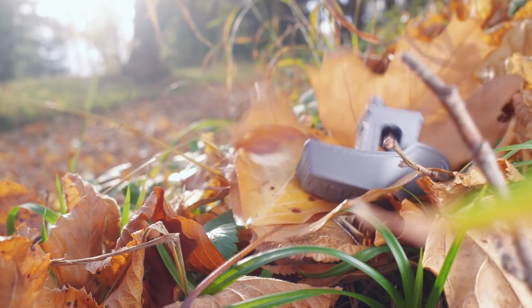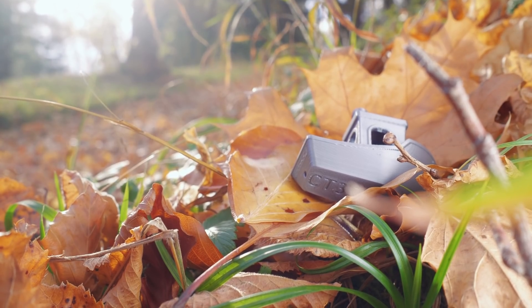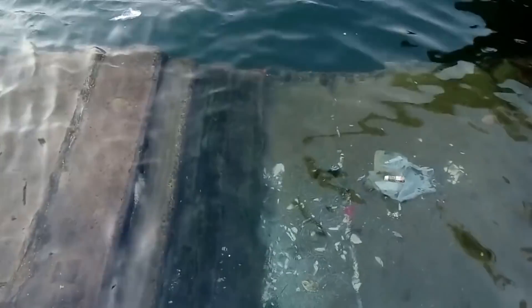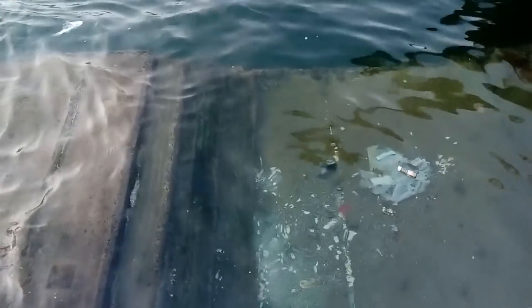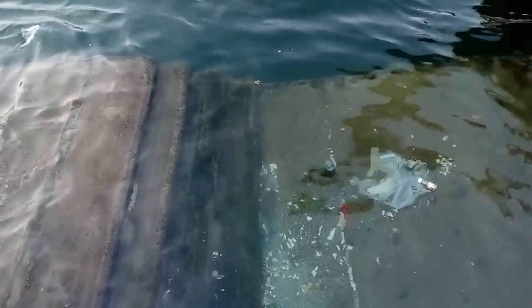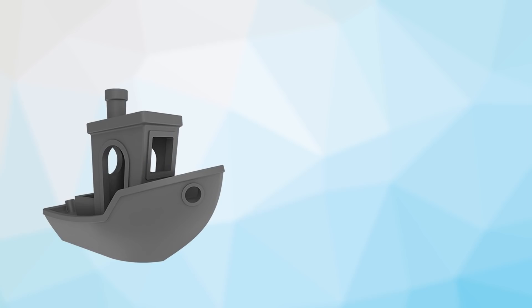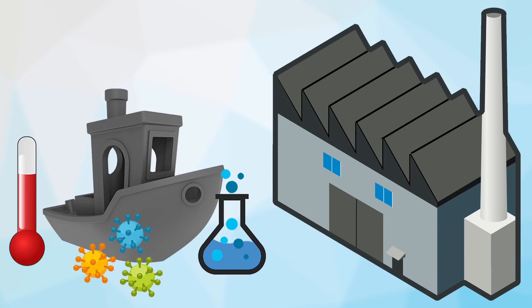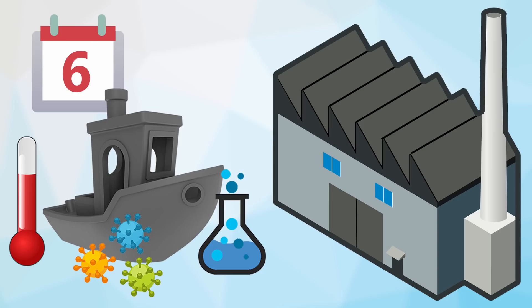The enzymes that could break it down are virtually non-existent in nature. Throw away PLA in the forest and it will stay there unchanged for decades. Throwing it into the ocean doesn't work either, as we've seen with the seawater test. So if PLA doesn't degrade naturally, then how else? That brings me to the main issue with PLA. It's only biodegradable in composting facilities, where it must be constantly heated at around 60 degrees Celsius, within certain high oxygen levels and with correct microorganisms present. Even then, it can still take over six months before it's fully degraded. These conditions can only be achieved in dedicated recycling facilities.